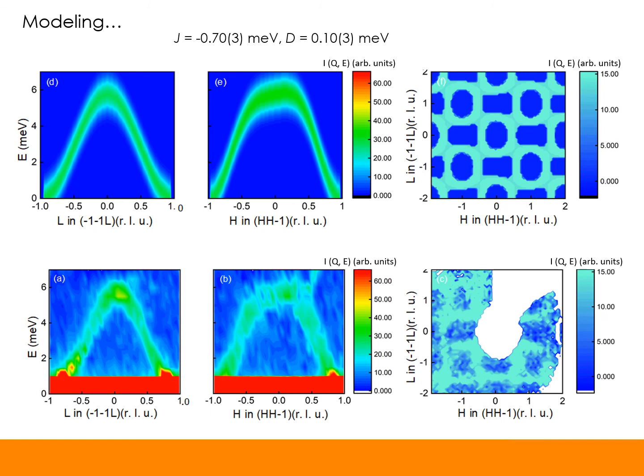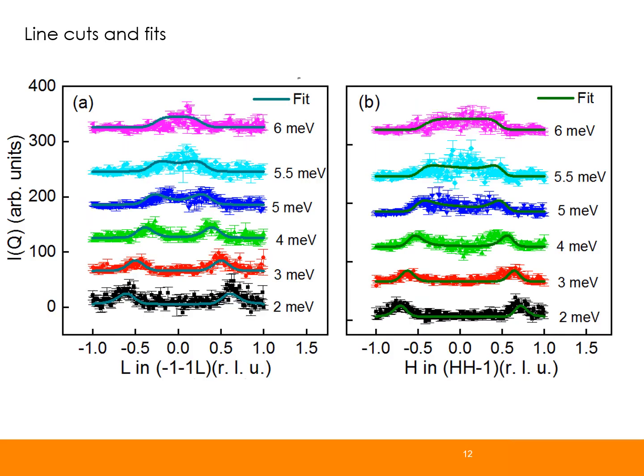Based on these simulations, we observed the nearest neighbor exchange coupling around 0.7 meV, which is strongly ferromagnetic, and the DM interaction is around 0.1 meV, meaning that the DM interaction is around 15% of the nearest neighbor exchange interaction in this material. Now I'm showing the line cuts and the fit of the line cuts along the high symmetry directions 001 and 110. The fitting of the constant energy cuts from 2 meV to 6 meV along these two high symmetry directions also indicates that the model is completely capturing the features in this material.